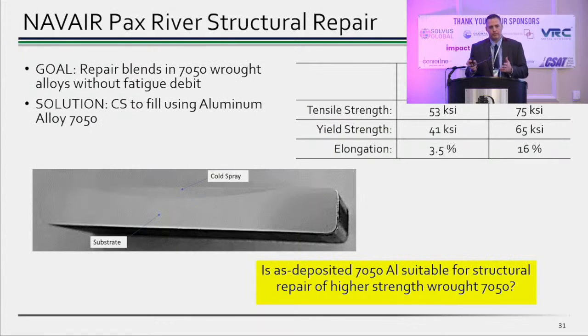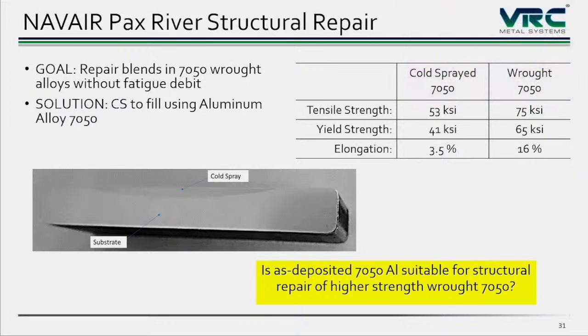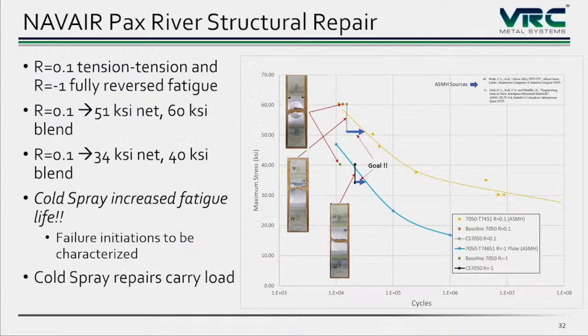So now let's look at a different scenario. If we take that same 7050 material that we just talked about, the cold sprayed material, but now we apply it to a 7050 substrate instead, you can see that the wrought 7050 material has a higher strength capability than the cold sprayed material and a higher ductility. So now can we still use this for some sort of structural credit? Well, we find out we can. In fact, the baseline materials here are this green dot and this little red dot up here.